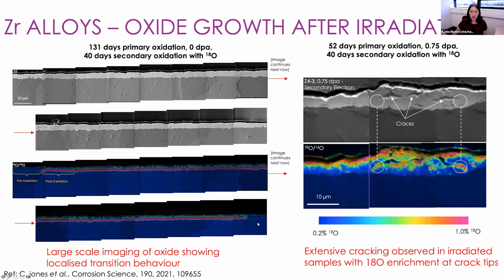Here, the oxide is still protected. Water cannot penetrate through it. We only get a small amount of oxygen incorporation on the outer surface. So this is where we can show large-scale imaging. We're able to image over vast areas of the sample. And the key thing here with using isotopes as well is that without using isotopes, we wouldn't be able to determine which bit of oxide had just formed in that 40 days prior to it.